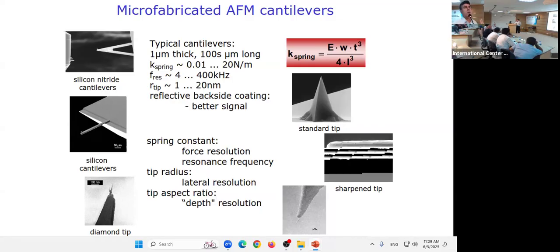Each cantilever has its own resonance frequency. So what I normally urge Saira and Shuja is that you will have to lock the frequency after each measurement. Whenever you withdraw your cantilever from the sample, before engaging it to the surface again, you lock the specific frequency. The reason is that when the cantilever is coming to the surface, something from the surface can attach to the cantilever. Once something is attached to the cantilever, the resonance frequency will change. And if you are not locking the new resonance frequency, then you will generate artifacts.